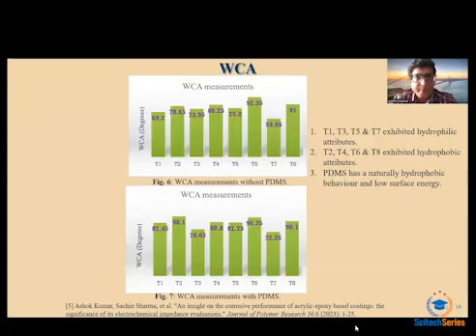So the second one will be the water contact angle. So in this approach, two sets of results were taken. Figure 6 illustrates the contact angle measurements without the inclusion of PDMS, and we wanted to compare with another set of results with the inclusion of PDMS. And we could easily see over here how significant the inclusion of PDMS was.